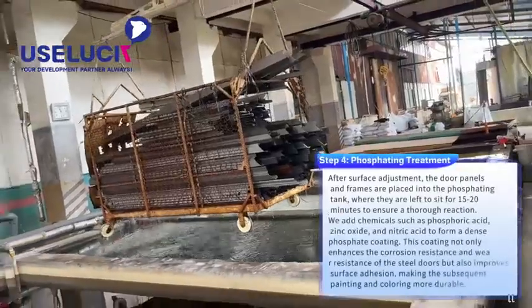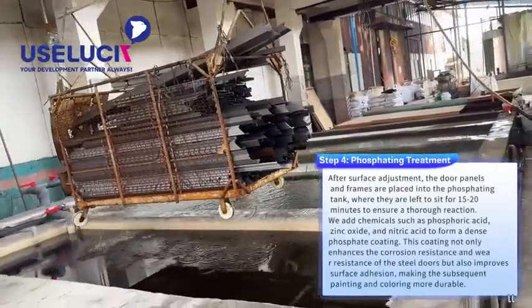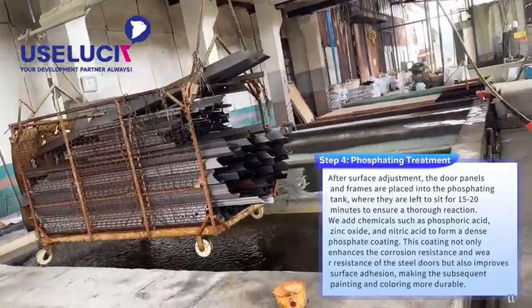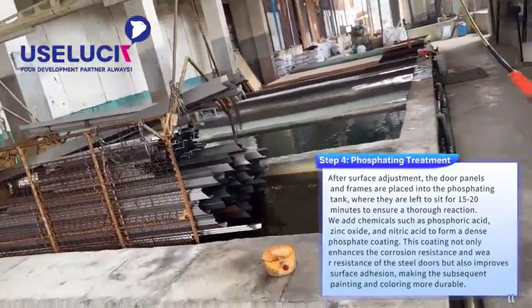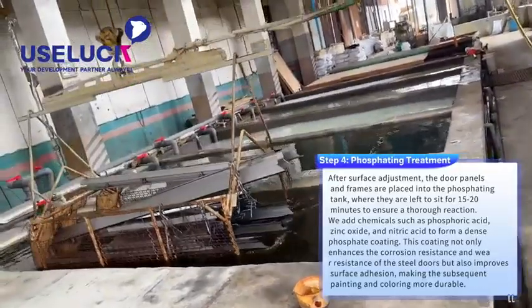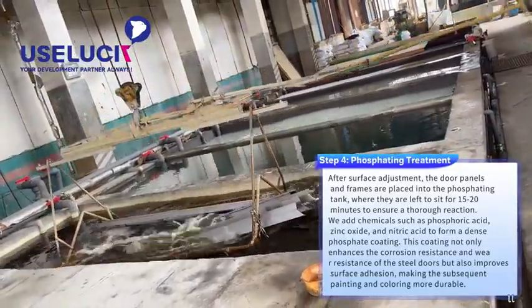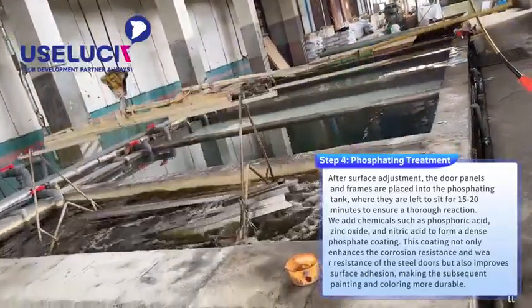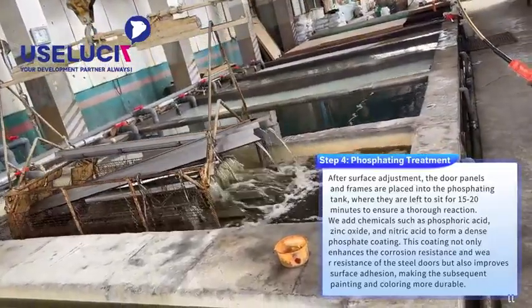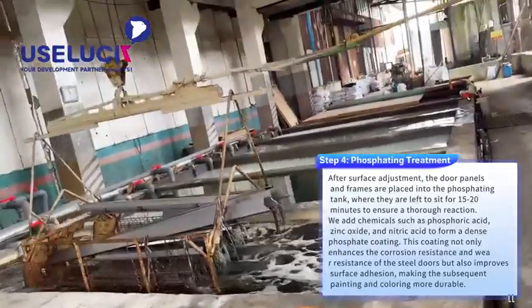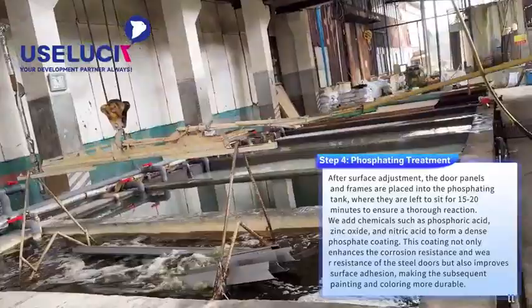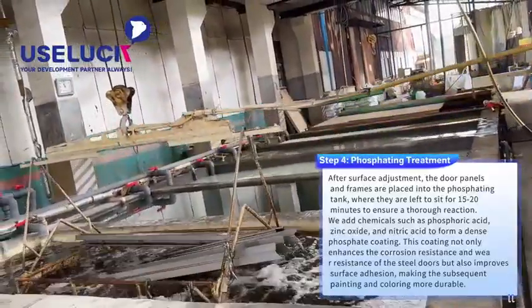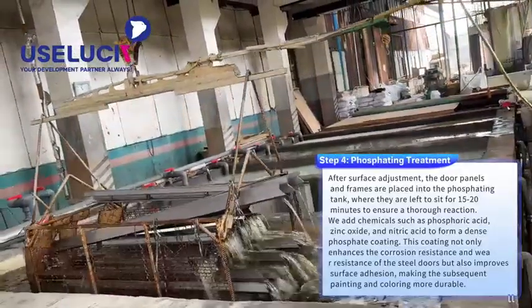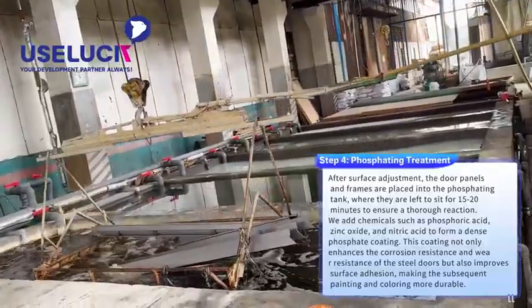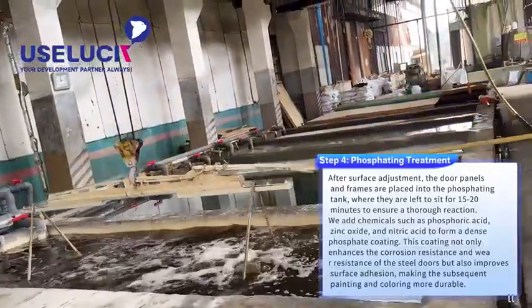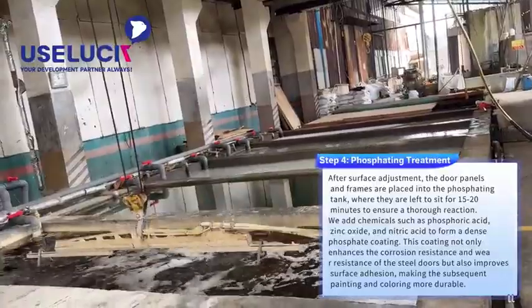Step 4. Phosphating treatment. After surface adjustment, the door panels and frames are placed into the phosphating tank, where they are left to sit for 15 to 20 minutes to ensure a thorough reaction. We add chemicals such as phosphoric acid, zinc oxide, and nitric acid to form a dense phosphate coating. This coating not only enhances the corrosion resistance and wear resistance of the steel doors, but also improves surface adhesion, making the subsequent painting and coloring more durable.